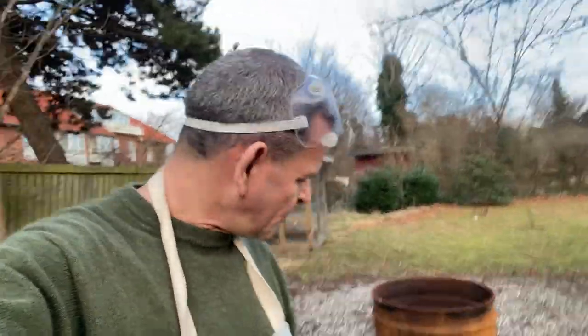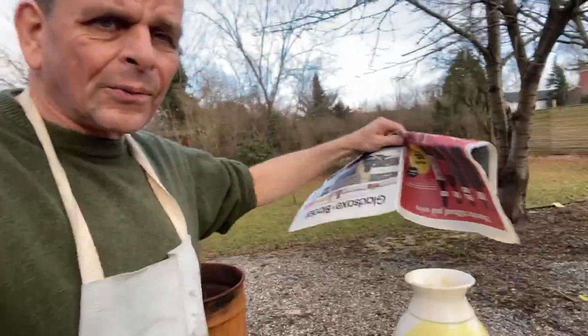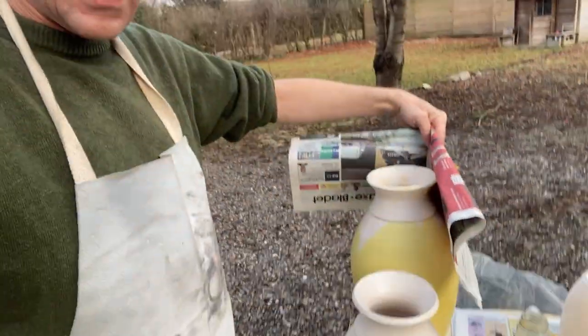I'm going to try something I actually did successfully in a Raku kiln — I'm going to wrap newspaper around the top and then seal it with tin foil. What I want to create is a black top. By wrapping the newspaper and tin foil, it will burn, and because of the tin foil, the carbon won't be able to escape, so it's going to attach to the clay. Because of the oxidation-reduction in there, it should turn black.